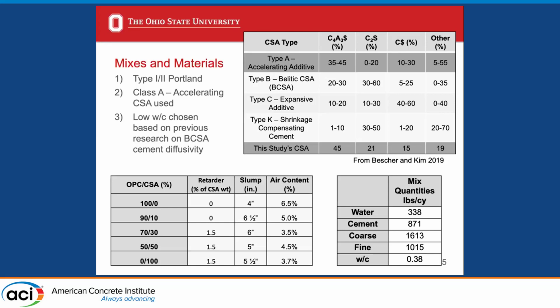We cast our mixtures with, you can see the mix design quantities on the right side here, a pretty low water to cement ratio. Previous BCSA diffusivity literature had indicated that you get much better performance with CSAs at slightly lower water to cement ratios than what you could use with a Portland cement. So we wanted to start out on a good foot as far as durability, with a little bit lower water to cement ratio. As you can see from the chart here, we were able to obtain pretty good workability through use of a superplasticizing admixture, and we did successfully air entrain all of our concretes.